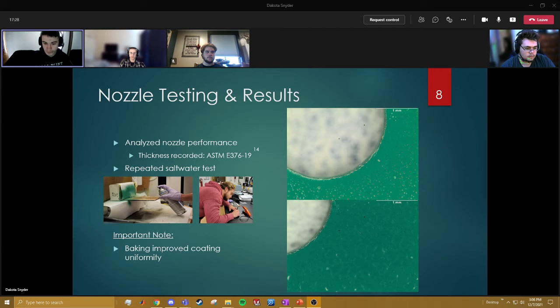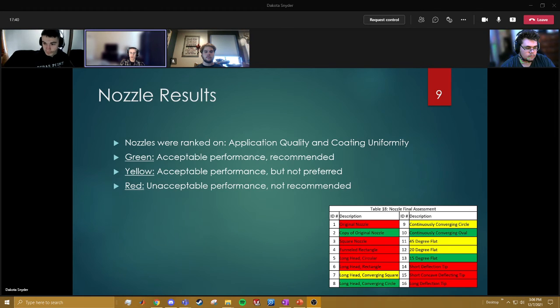Here's an example. Due to pitting being universal in almost every sample, it was used as a metric for nozzle performance. If you look at the picture to the right, it is a before and after image of the baking process. Nozzles were ranked based on application quality and coating uniformity. Application quality represents the viability of spraying the samples using each nozzle: clogging, non-optimized spray distance, and inability to reproduce consistent spray patterns.